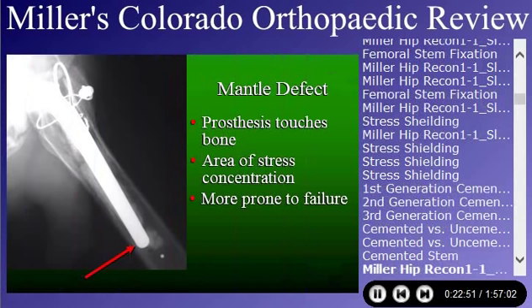Prostheses with mantle defects, which was shown by Bill Harris and Tom Thornhill, have a higher rate of loosening. And that's the only thing that they showed in terms of cement technique. So if you had a mantle defect, you're at an increased risk for mechanical loosening. And that goes back to Ranawat's stuff, that if you bottom out and touch, or you have a bloody interface where the cement slides out and the bone touches the prosthesis, that's where you get a mantle defect, and that's where you're going to get loosening.